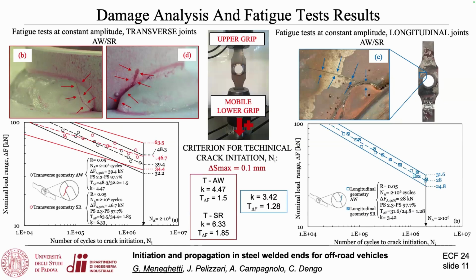Now let's start from presenting the data in terms of simply using the nominal load range, no stress analysis at all. Let's start from the longitudinal joints. You see a nice slope equal to 3 according to the standards, and you see that in the finite life, we do not have any advantage of the stress relieving heat treatment, and this has been found also in other research projects.